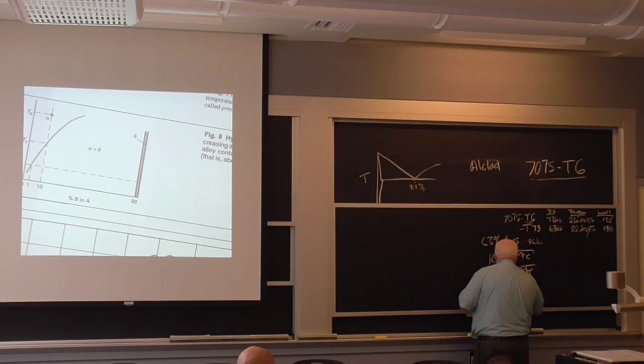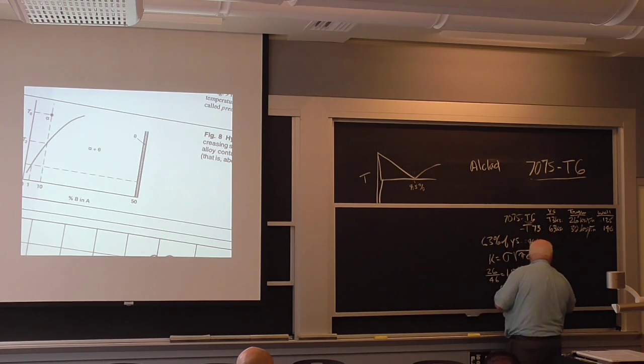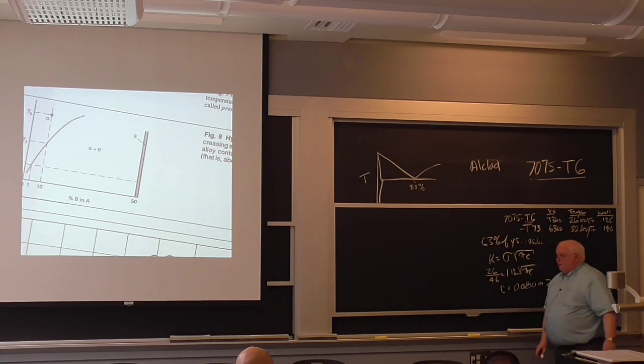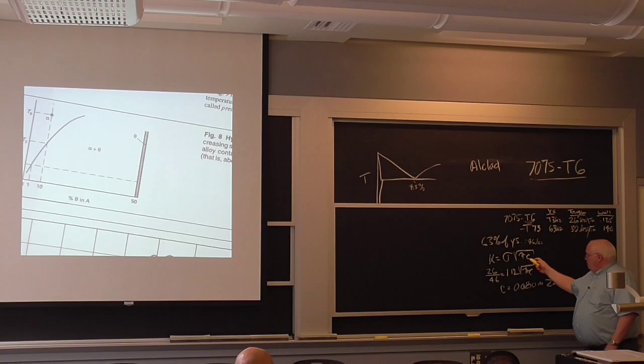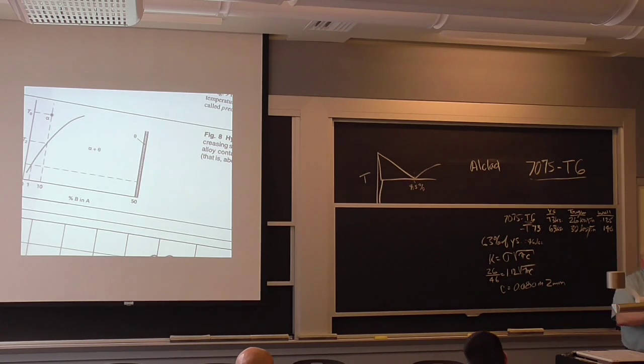If you solve that, you find the critical crack length is 0.08 inches, which is 2 millimeters. I told you the critical flaw size that we saw on the piece was 1 millimeter. What I didn't tell you, this is the half crack length, okay, for a crack at the surface. Internally embedded crack would be a 2C crack, but on the surface is a mirror plane. So when you do the fracture mechanics, it's the half crack length. So there it was. We proved the critical flaw size was 1 millimeter. We looked at the sample, and I could see it was 1 millimeter deep before it did a brittle fracture, okay? So that explained why you had a brittle fracture, and the whole thing split in two.